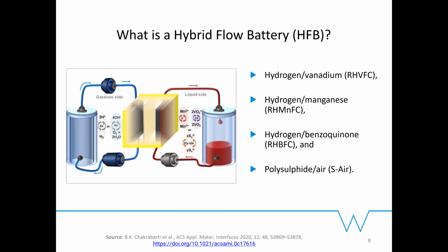But bromine has a lot of toxic properties, and it can also poison the hydrogen side catalyst, the platinum, due to migration via the membrane, which we are not able to yet stop. So more research requires to be done on this. So because of that, bromine usage is kind of limited and it's better to look into other kinds of chemistry, such as vanadium and manganese. But having said that, the hydrogen bromine system is already being commercialized in Holland by a company called Elestor.